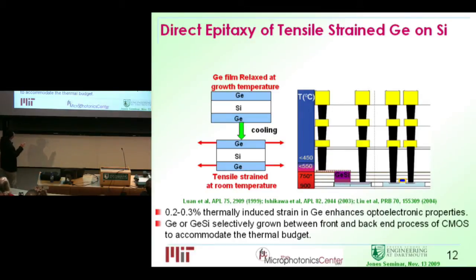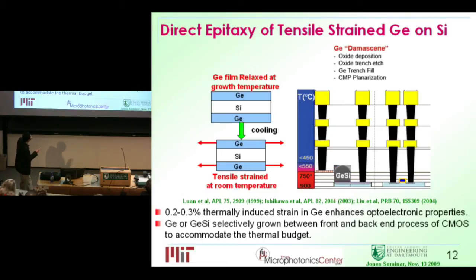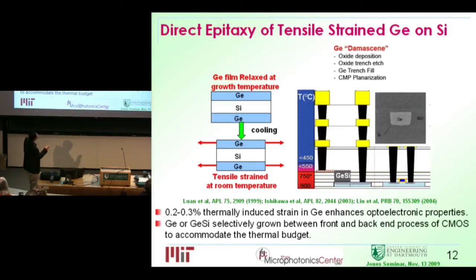So this right figure shows how you integrate this germanium silicon material into CMOS. What we do is we perform a selective growth. Instead of growing germanium everywhere on the blanket, we can actually open a little trench here with dielectric cover, and then germanium will grow selectively into this trench. This facet is due to the single crystalline nature of germanium, just as you see with diamond, because germanium is exactly the same crystal structure as diamond. Okay, and if you don't like it, you can actually polish it down, and this is a nice flat material you get, and you can make a device out of that. Okay.